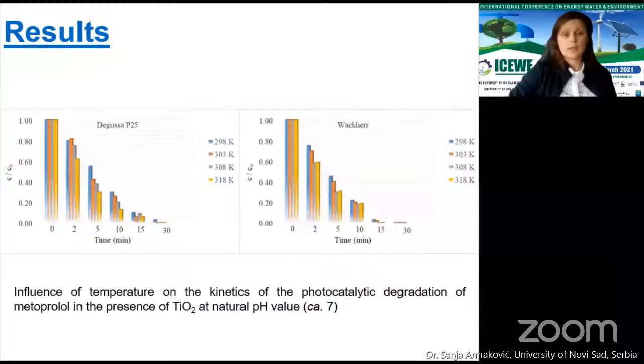And what did we get? The specific surface plays a significant role when it comes to the photocatalytic properties of nanostructured and porous titanium dioxide. The photocatalytic activity of Wacker was compared with the most commonly used form of titanium dioxide, Degussa, under the influence of UV radiation. The efficiency of photocatalytic degradation differs depending on the catalyst used at the same temperature and pH. Faster decomposition of metoprolol was established when the Wacker form was used, compared with Degussa.